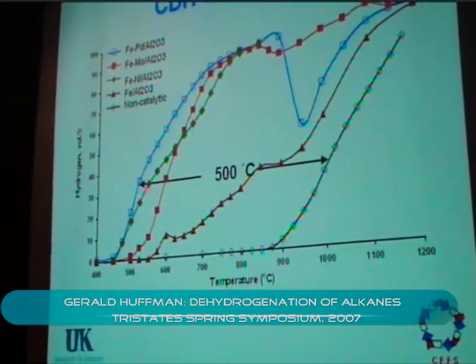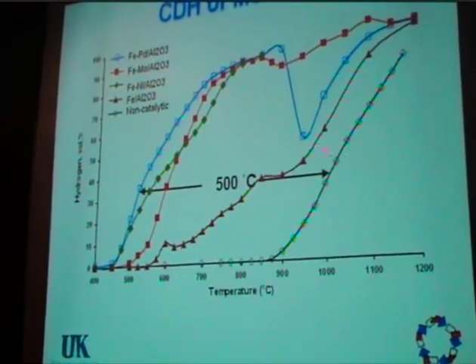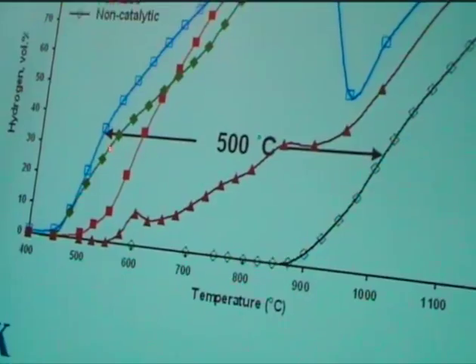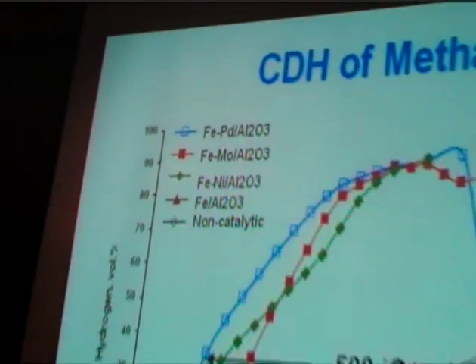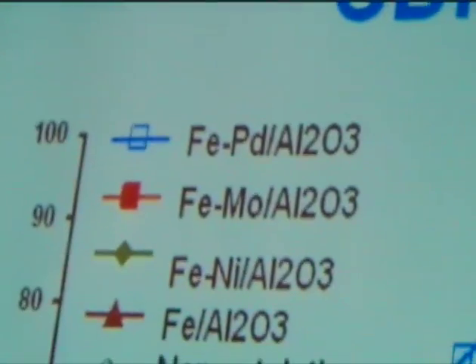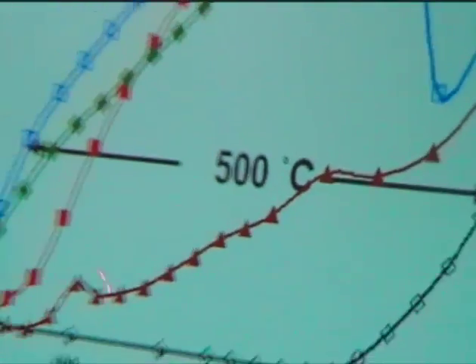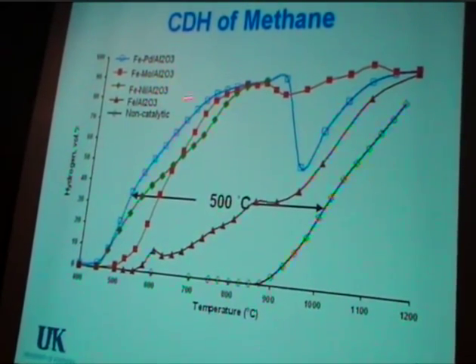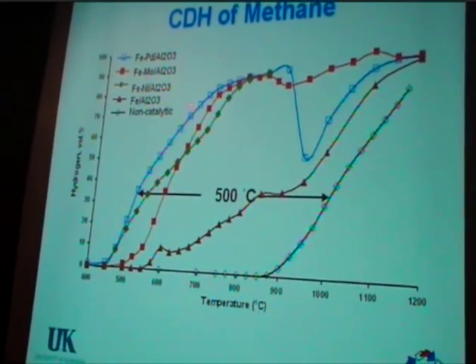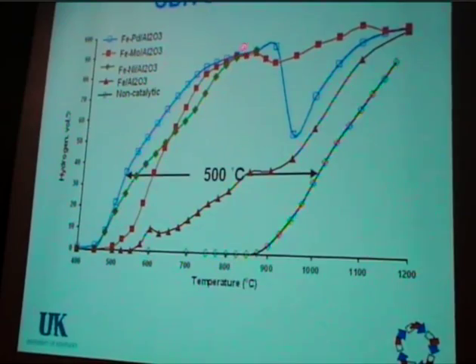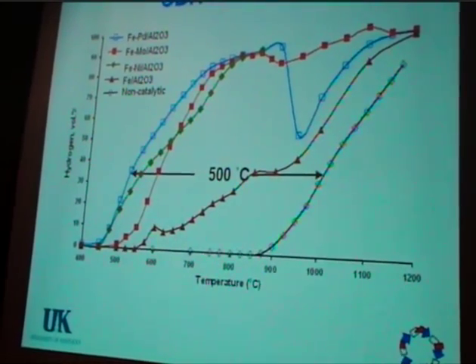As you can see, we've got a pretty big catalytic effect, about 450 to 500 degrees decrease in the decomposition temperature of methane from the thermal case. And in the most active region, from about 650 up to about 800 degrees C, we're producing about 70 to 85% hydrogen in our simple plug flow reactor.